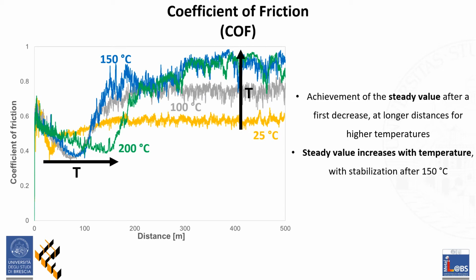Coefficient of friction plotted as function of the distance for every temperature investigated is reported in the previous slide. The higher COF value at the very beginning of the curve is due to the presence of great asperities. Then, after a decrease, a COF steady value is reached for every temperature, at longer distances as temperature increases. Moreover, the steady value gets higher with temperature, going approximately from 0.6 to 0.9. However, a stabilization is detected after 150 Celsius degrees. Changes in this curve reflect what is happening microscopically regarding the wear mechanism, and it will be analyzed later through SEM images.